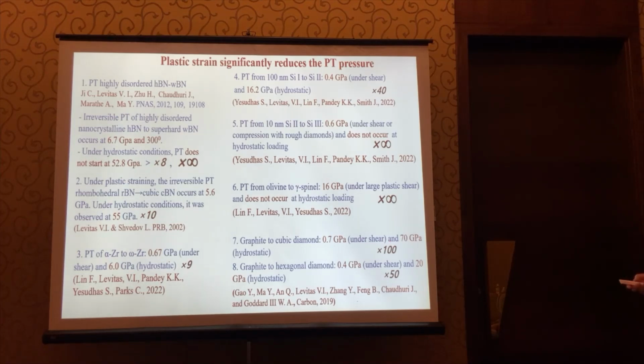And some phase transformations don't occur under hydrostatic condition at all. For example, silicon 3 does not appear under hydrostatic condition, but under shear we obtain it at 0.6 GPa. Also, olivine to spinel does not occur under hydrostatic condition and room temperature. We obtained it at around 16 GPa. And all this drastic reduction in pressure has potential technological application and some implications to geophysical problems.